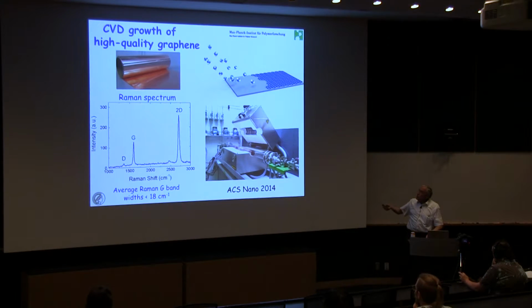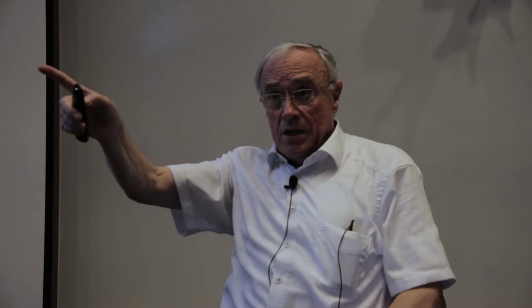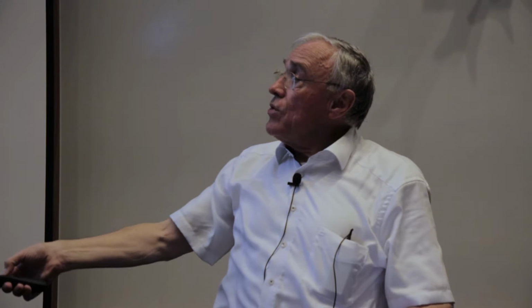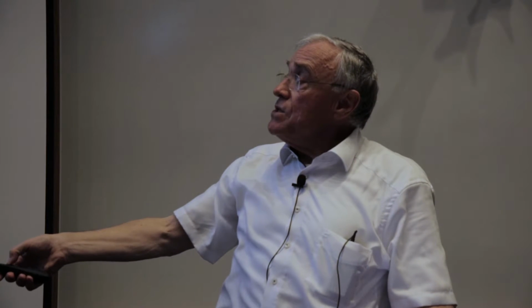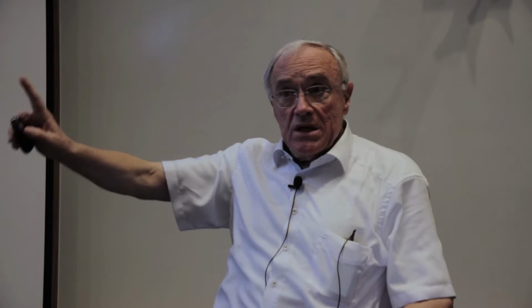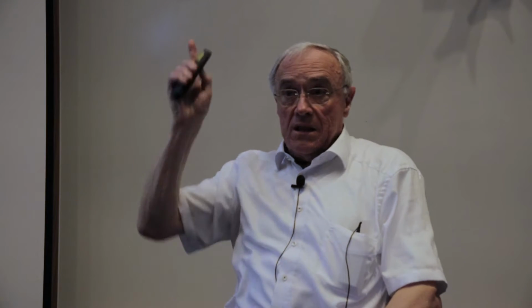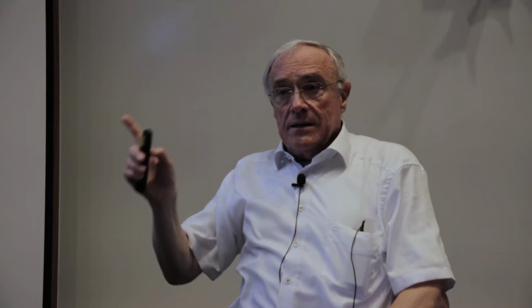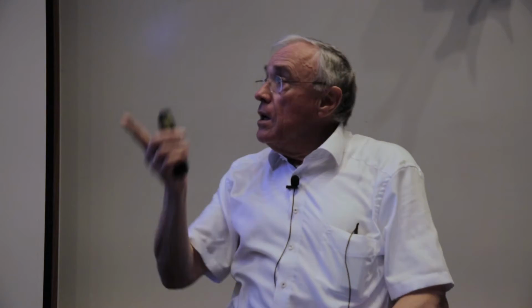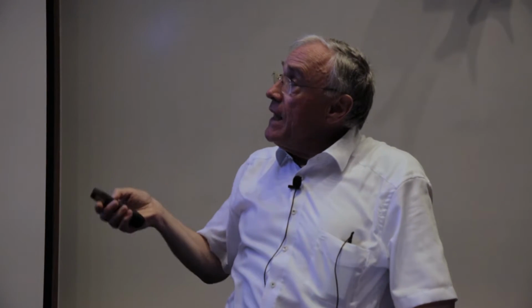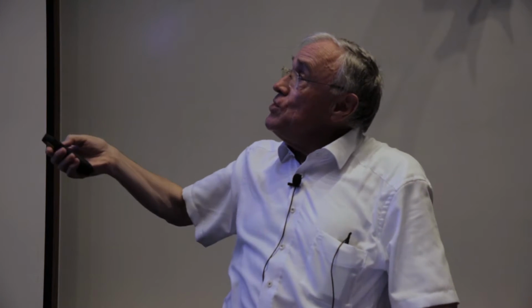This is a commercial machine, the Black Magic machine, nothing special. But we make ultra pure graphene, with some tricks, also regarding the charge carrier mobility, which is 500 square centimeters per volt per second. This is good stuff. Bottom up. This is another bottom up. And again, the animation doesn't work.